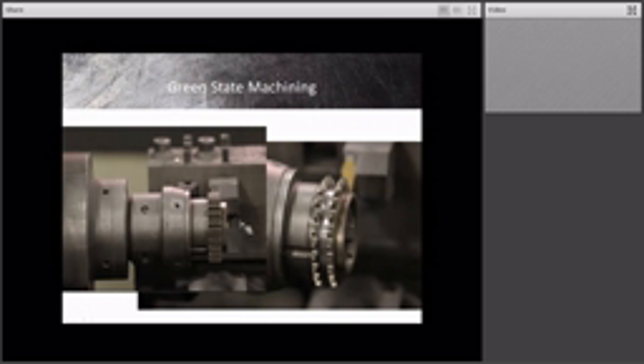Relatively unique in our industry is what we do with our green state machining. We worked many years ago with a major powder supplier to develop a process for machining parts prior to the sintering operation. In other words, when they're still basically like a raw cookie that could be broken. Effectively what happens is that the particles are glued together, and then the machining can take place, as you see in this component, where there's actually a groove cut between a full-length tooth.